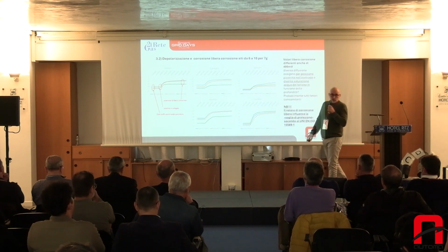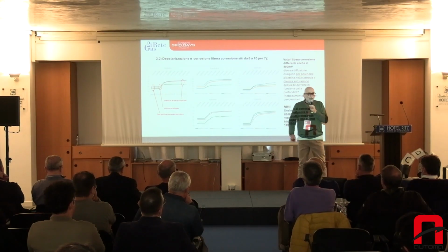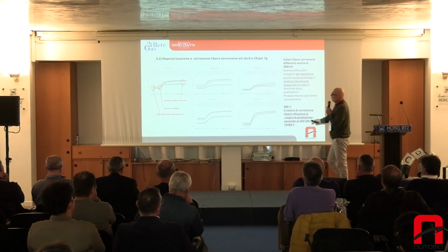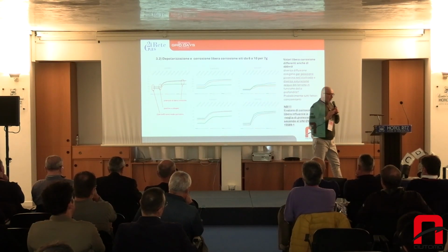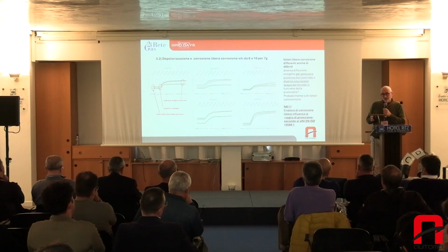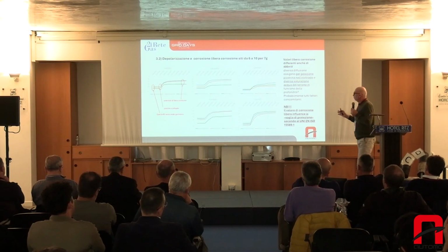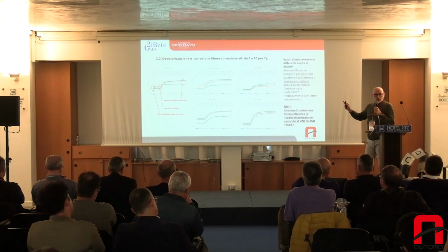We can see the potential differences in natural potentials are significant. 200 millivolts. So depending on the site, the natural potential of plates can vary significantly. And we need to bear this in mind.